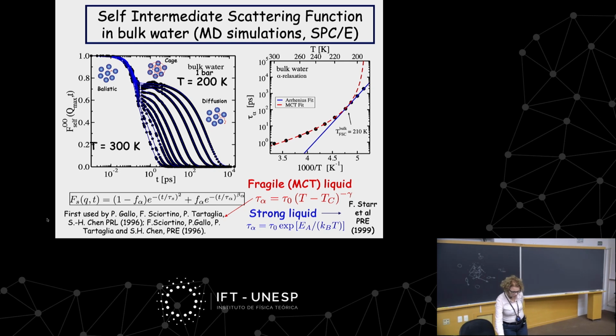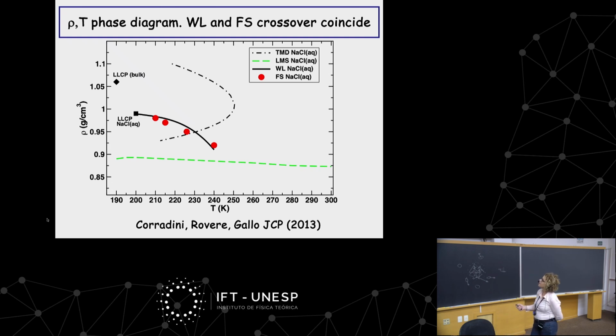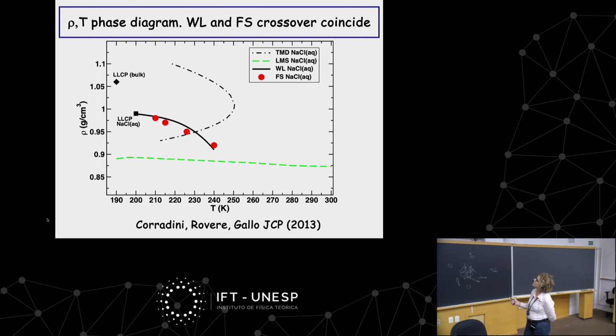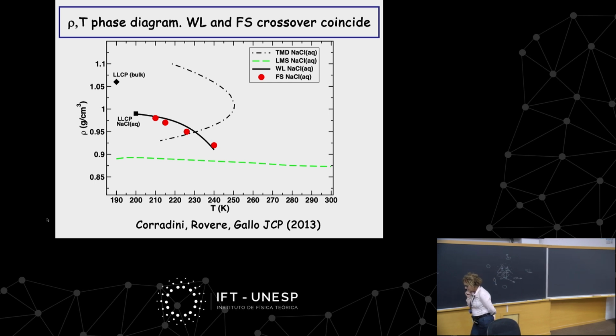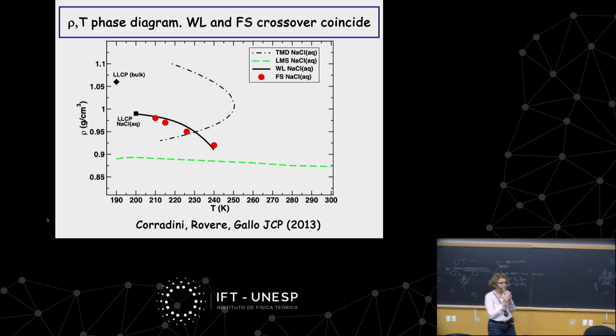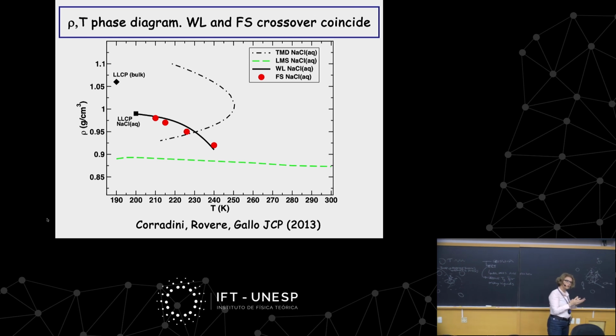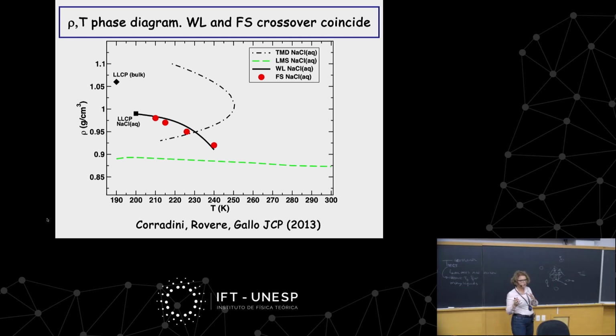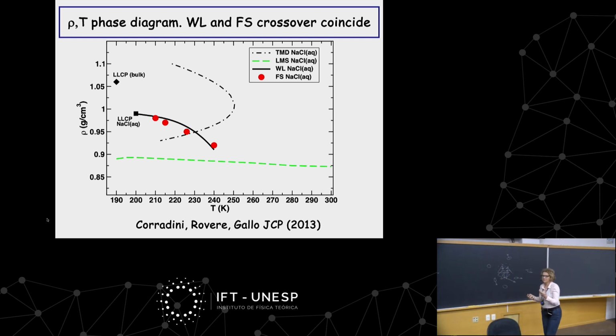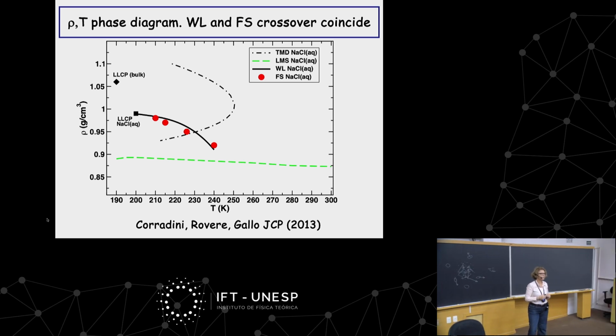So water is becoming like a common gas transition, but there is also an interesting fact, which is that this crossover from fragile to strong happens exactly on crossing the Widom line. So the dynamic crossover happens on the Widom line, or very close to the Widom line. This has to do with the fact that the Widom line separates a region in which the fluctuations of high density prevail from a region in which the fluctuations of low density prevail. And when you have high density or low density, you also have different dynamics. So this crossover in dynamics is related to this particular thermodynamic feature of water.